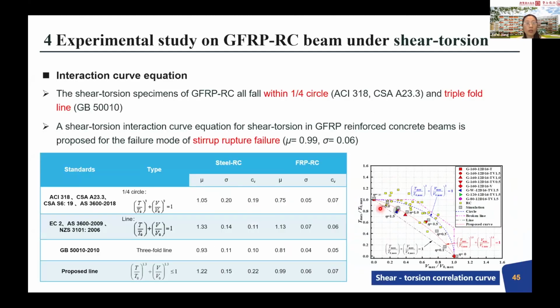And now here I want to show you that, based on our test results, we found the interaction between shear and torsion shows data scattering here, and also including our numerical result, which is between the interaction curve for steel RC beams, and this 45-degree line is for the elastic theoretical results. So that means the elastic behavior of FRP has a significant effect on the shear and torsion interaction.